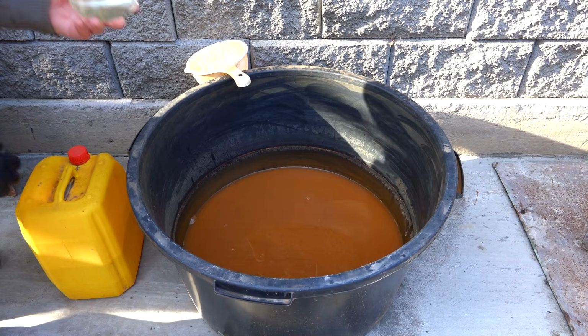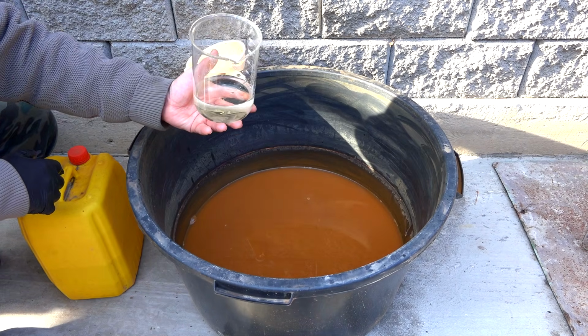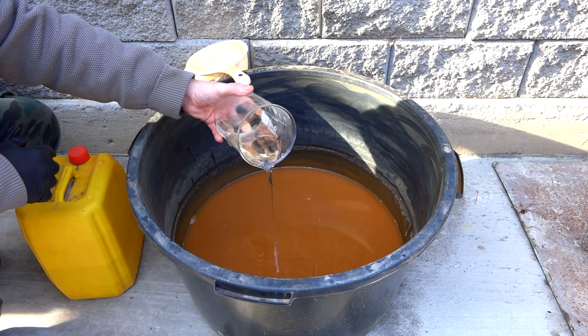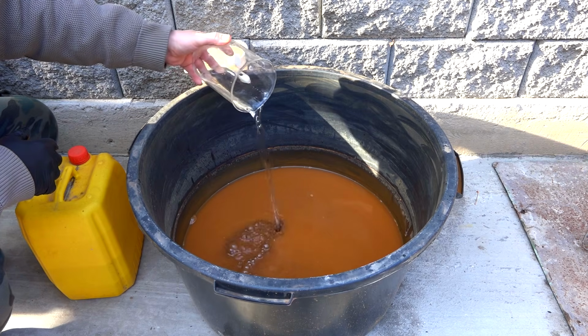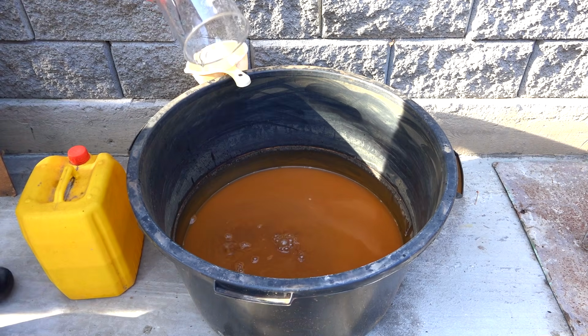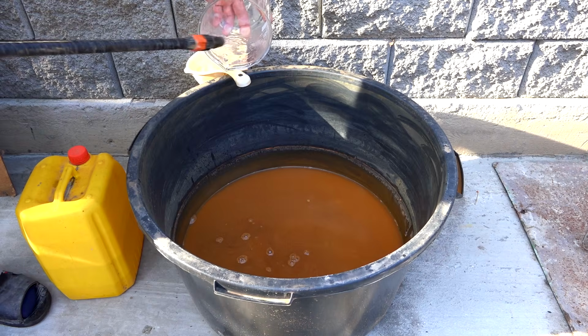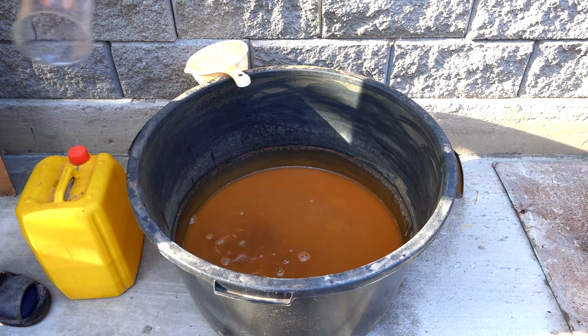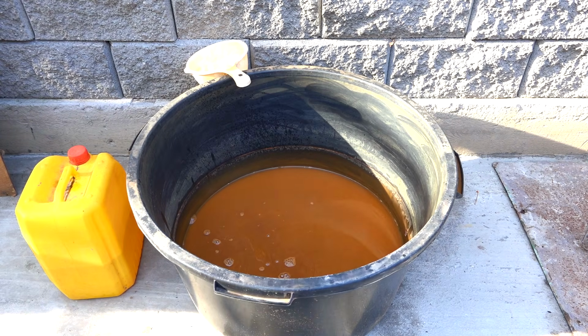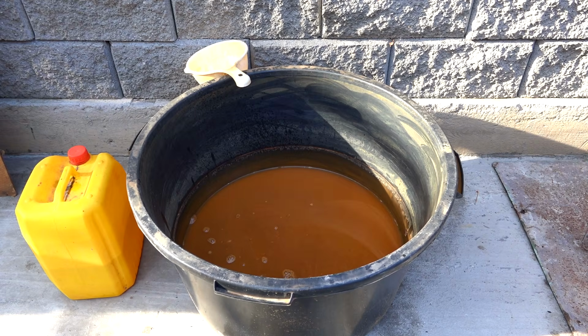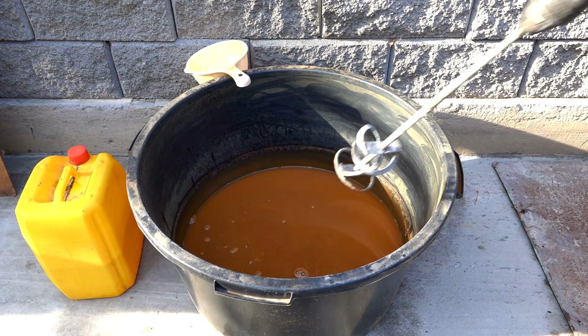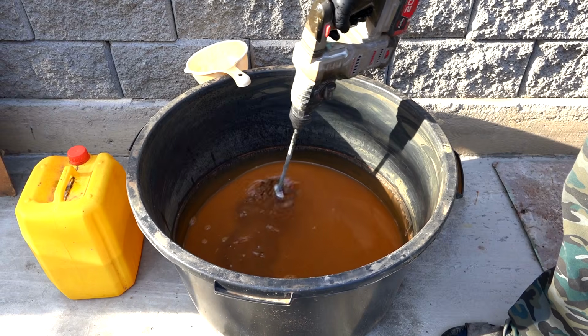First, the pulp needs to be stabilized, otherwise the gold won't be extracted. To do this, I add special chemicals, additives, to the concentrate. Now everything needs to be thoroughly mixed, the added chemicals prevent the particles from clumping and keep them suspended. I stirred this rusty pulp for about 5 minutes and then let it sit for a few more minutes for the best results.